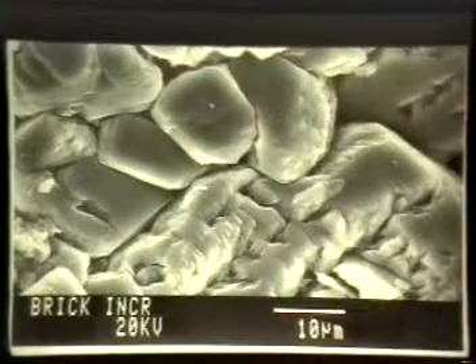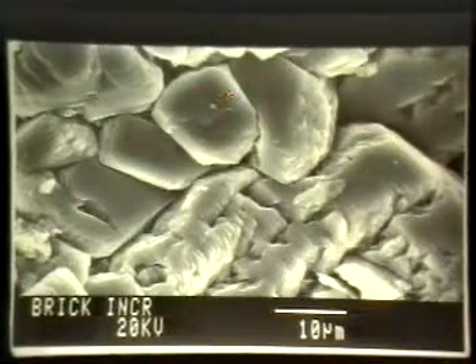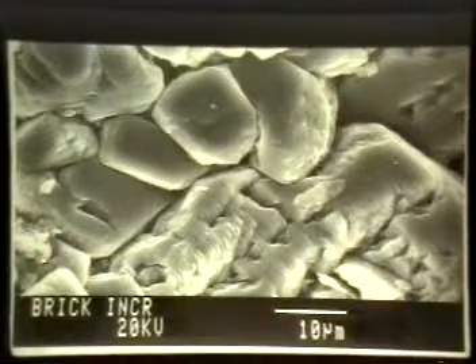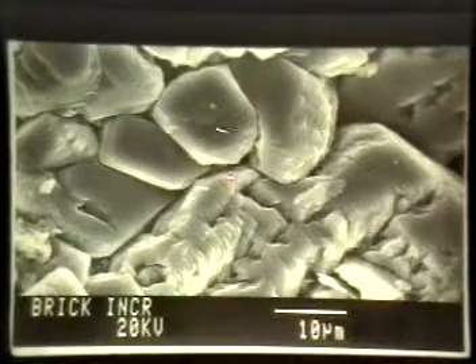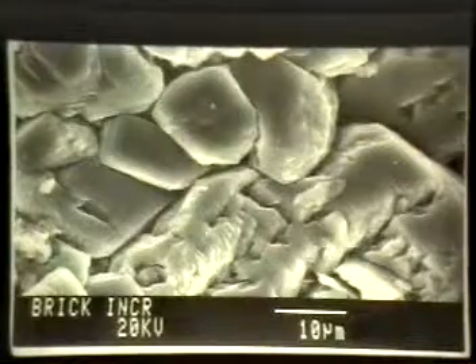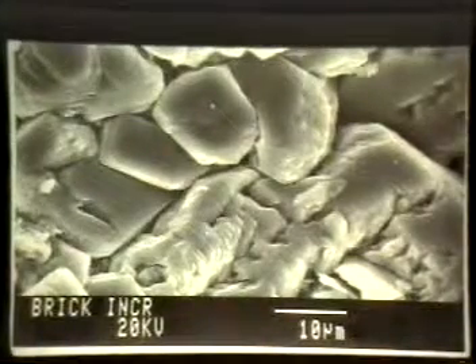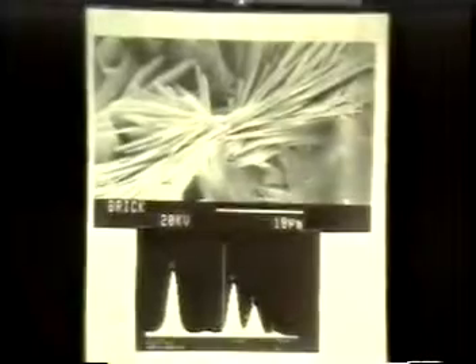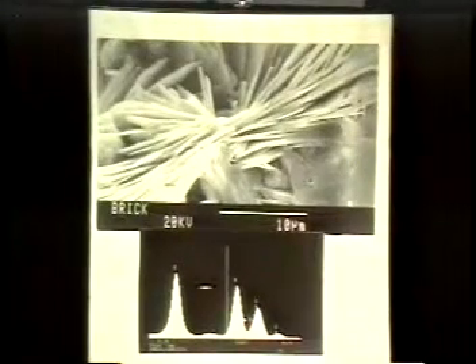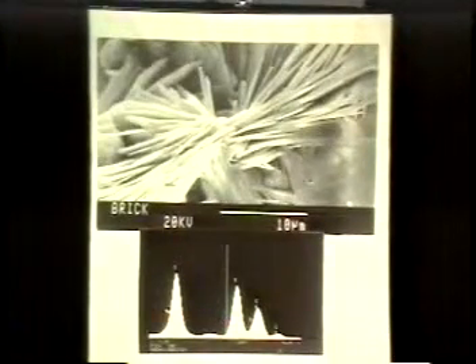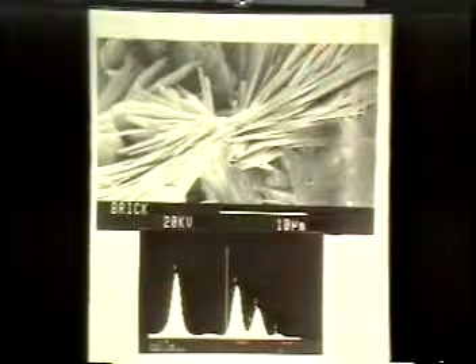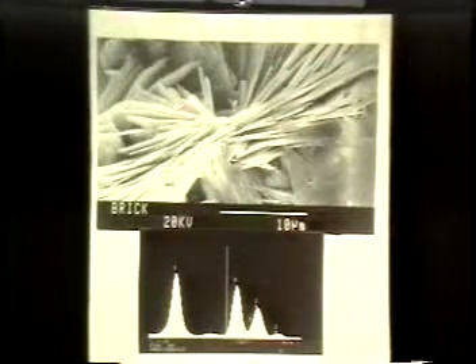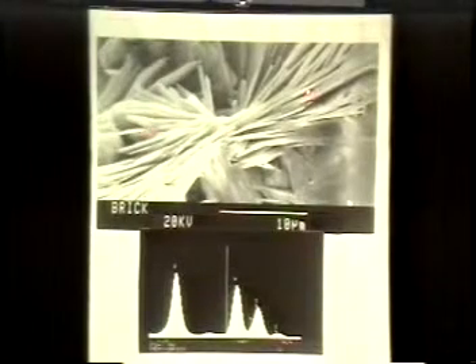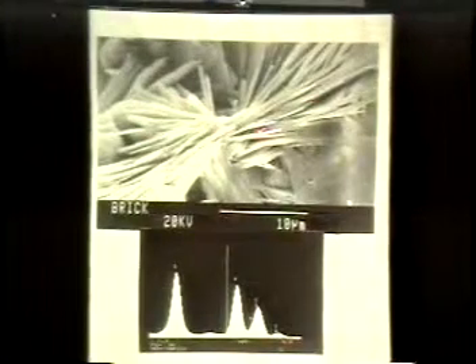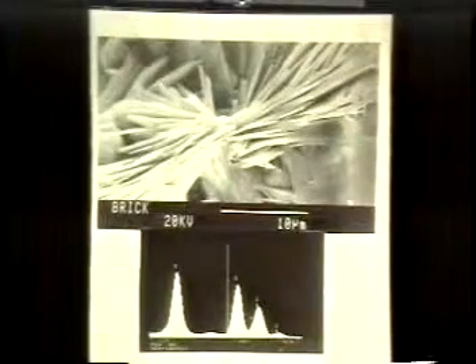Next, please. When you identify the efflorescent salt, this is one salt we found, gypsum, massive gypsum crystals. It's an expansive salt, and this is what creates the expansion and scaling on the surface of the structure. Next, please. Another type of salt we found in this case was calcium potassium sulfate, or syngenite. Again, it's an expansive salt and creates problems. You can see expansion occurring in all directions when you have this type of salt precipitation on the surface.